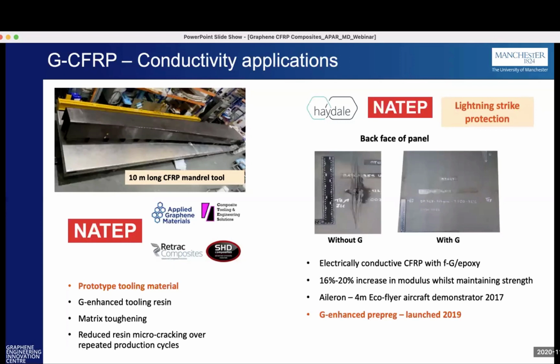So this is a lightning strike. Again, this is with a company called Haydale. So this was looking at trying to replace the copper wiring in the wings for lightning strike on aircraft. So you might say increase electrical conductivity, a carbon fiber reinforced plastic with a graphene enhanced epoxy. You can see there on the left, without the graphene, the scorch marks, and the one with the graphene has no scorch marks whatsoever from the testing, so it didn't really touch it.